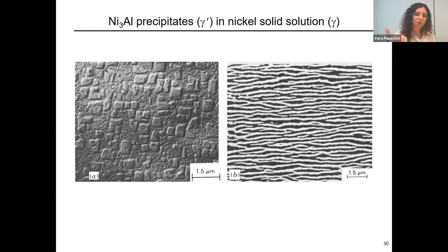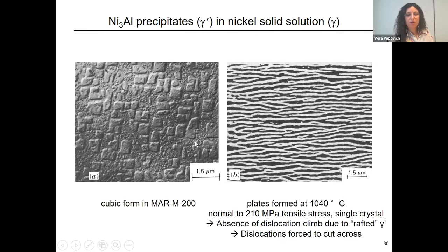Similar shapes you can find also, for example, for carbides in this material. And here you see, let's see if this moves, a nickel-based superalloy, and this is relatively large. This is the largest gamma prime I've actually seen, this kind of cube in the range of a micrometer. Normally, if you look into Inconel 718, 738, 625, they're in the submicron range.